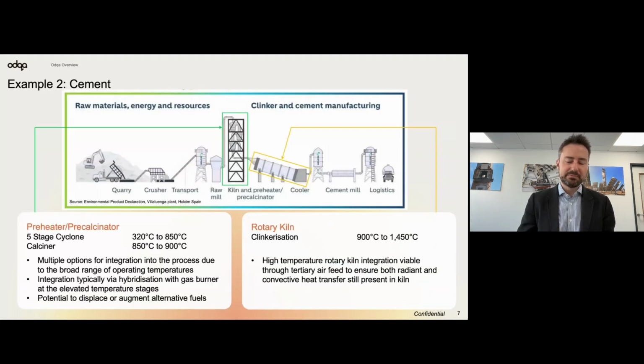Our second example is in the world of cement. Cement is a huge emitter of carbon dioxide. I think the industry just on its own is around about 8% of total global emissions. If you look at the key energy consumers for the cement process, there's preheating, and then there's also the rotary kiln. So the preheater, this is from 320 degrees to 850 degrees, and then lower down the preheating stack, it's at an even higher temperature, 850 to 900.